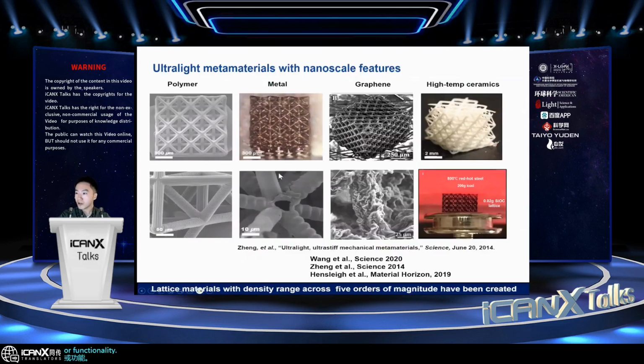Although the baseline technique can only process polymer, through advanced material feedstock synthesis or post-processing, you can convert this single material into other materials as well. So here's the polymer, but in that paper, we also show that you can do metal deposition and etch away the polymer, leaving behind metal lattices, or even graphene metamaterial.